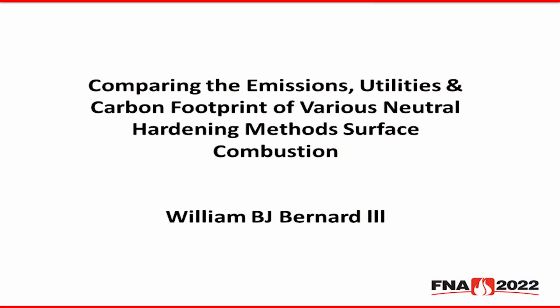Other things to do to reduce carbon footprint: tune your burners. There are too many burners out there that are untuned. You've got to get them to 5 to 10% excess air. Repair your cracks and gaps and broken insulation. Clean your heat exchangers. These are all energy efficiency things that reduce the amount of energy you use, which will then eventually reduce your carbon footprint. Focus on energy efficiency. Focus on increasing production per pound of CO2 released, or per kilogram of CO2 released, or metric ton of CO2 released. That in general will lower your carbon footprint compared to someone else.